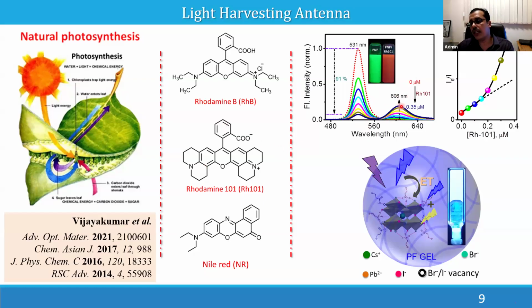So finally, you are getting a beautiful emission from the rhodamine 101, even at a very, very low concentration of 0.35 micromolar. In percentage terms, it is hardly 3 or 4% of the material that is enough to get like a 91% quenching of the donor and significant emission from the acceptor.